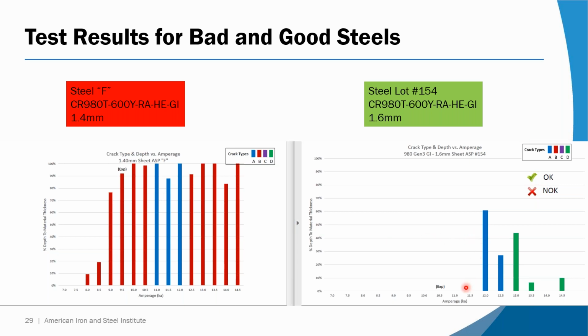The material on the right had no cracking below expulsion. Really nice thing to see. Above expulsion, we did see some cracking, but not the red type cracking. We only saw blue, which is type A, under the electrode, and then green, which is in that transition space between the electrode and the parent material that the electrode only touches during indentation.